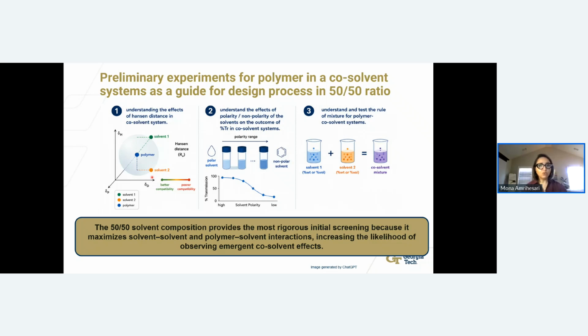We also wanted to understand and test the mixture of polymer in a co-solvent system. So what ratio to run, right? This initial screening was performed at a 50-50 solvent ratio because this composition maximizes the influence of both solvents at the same time. As the most interaction-rich composition, it provides the highest likelihood of revealing some of these emergent phenomena in the co-solvent system, such as co-solvency, co-non-solvency, or other phenomena that might happen. It also gives us a baseline: if this is happening, can we run the other ratios?